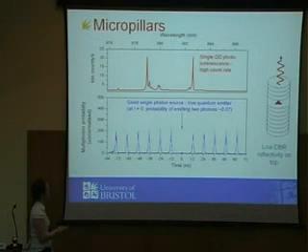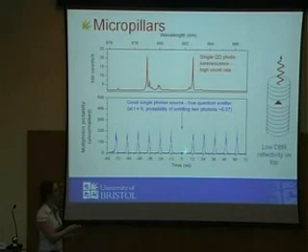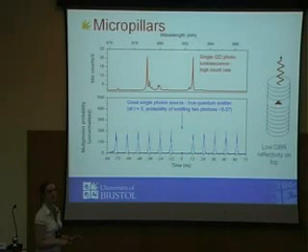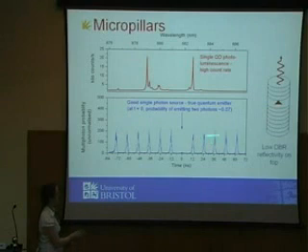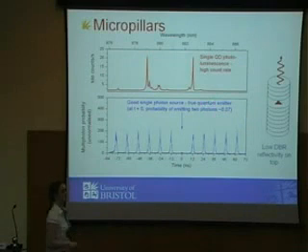Here we're showing a long time, with t equals 0 here. If you look 12 nanoseconds later, we measure a first photon, that's our start signal, and then we see the next photon 12 nanoseconds later, because that's when we have our second pulse. This is why we see a series of peaks here. But if you look at exactly t equals 0, the probability that we have 2 photons arriving at the same time isn't 0, but in fact about 7%, because these devices aren't perfect.